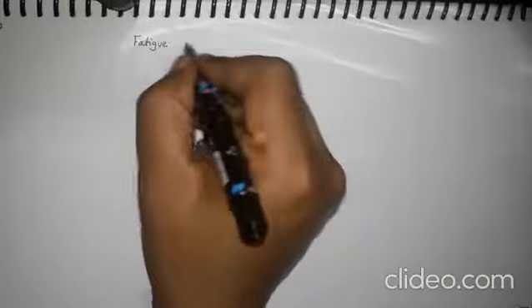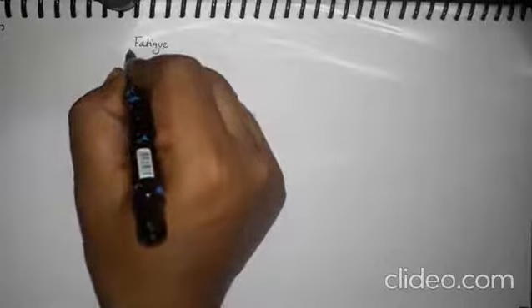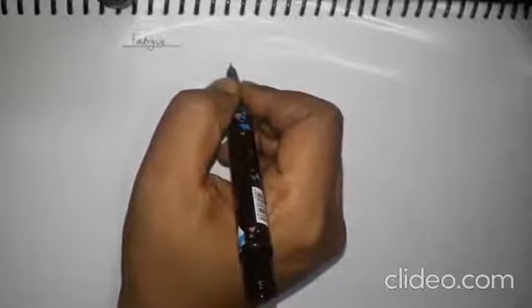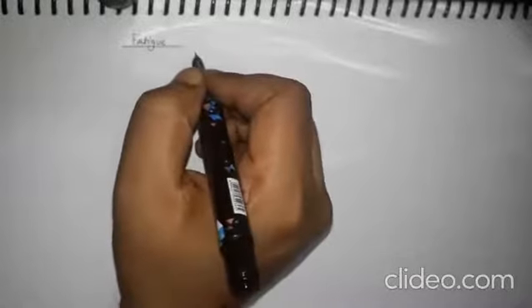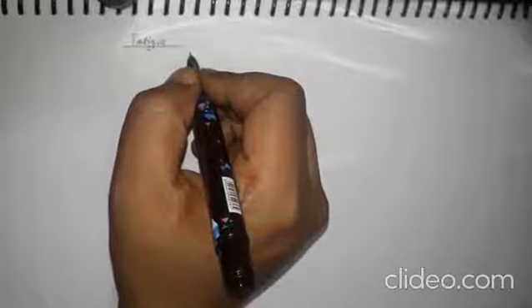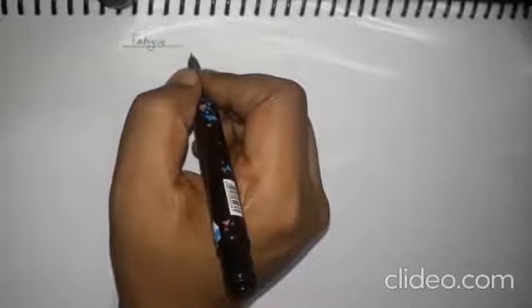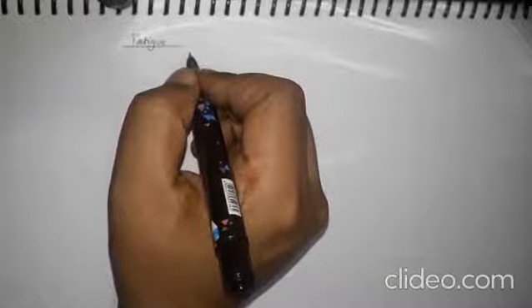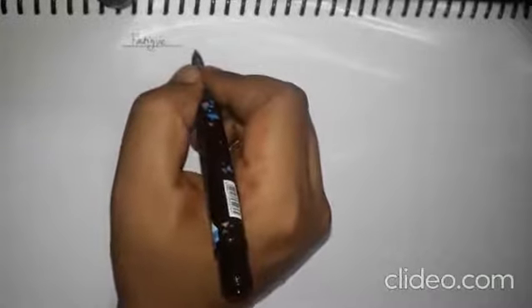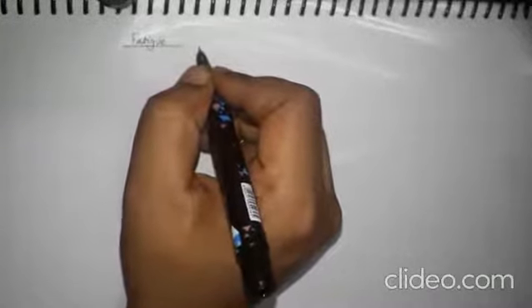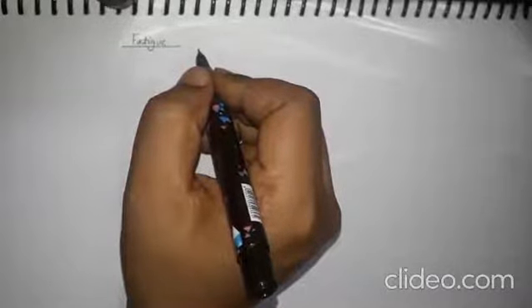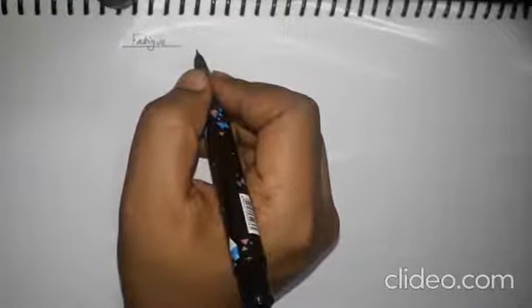So I'm not writing fatigue failure, but just fatigue, so that we talk about fatigue without focusing too much on the failure. But the reason why we are studying it is because components usually fail due to this kind of deformation. Fatigue failures, the failures which happen because of this kind of behavior, are usually subtle. So you wouldn't know if the material is getting damaged, and the triggers for this kind of damage are usually unavoidable.